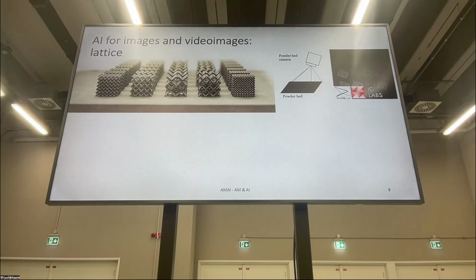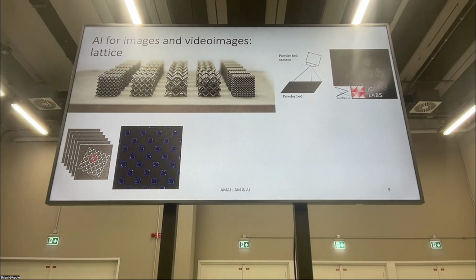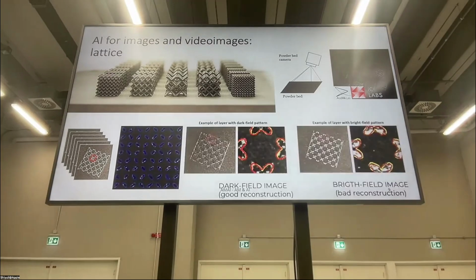So what we have been doing is taking images in real time from the machine that is producing this lattice structure layer by layer. And we have been developing solutions that are able to detect, layer by layer, the actual shape of the melted zone. In this case, you are just seeing a video that is showing each layer and the detection algorithm that is able to detect what is melted with respect to the loose powder. So it's basically able to detect the geometry of the lattice structure at that specific layer.